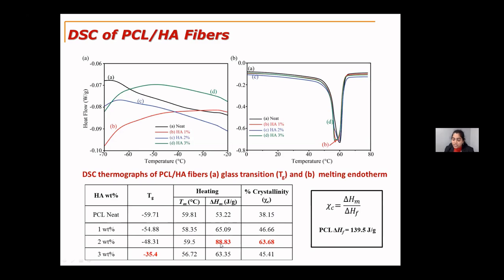However, 2 weight percent has shown higher crystallinity compared to 3 weight percent. This is because, as I discussed already in the characterization of the fibers, when the filler percentage increases, the particles agglomerate, and when these particles agglomerate, they create a molecular disorientation in the polymer nanofiber chains, and that creates defects in the structures. That deteriorates the properties of the nanofibers. As a result, we can see that the crystallinity decreased for the fibers with 3 weight percent.